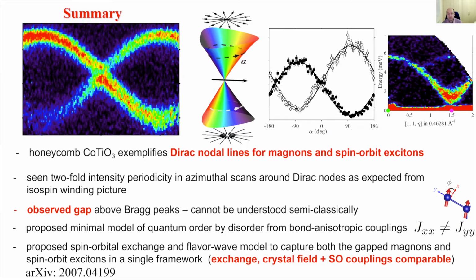The phenomenon of selecting a unique ground state from a classical manifold of degenerate ground states is of fundamental interest in frustrated magnetism, and cases of order by disorder that are really clear, found experimentally, are very rare. This is quite a unique circumstance in which the exchange, spin-orbit coupling, and crystal field interactions are all comparable. So most likely, the ground state selection is through virtual crystal field transitions. In other systems, such as erbium titanate, which is quite a canonical example of order by disorder, the separation of energy scales is much larger. So probably there, that mechanism is not so relevant. But here, in our opinion, it looks like the most relevant.